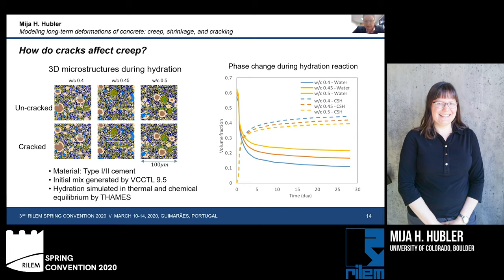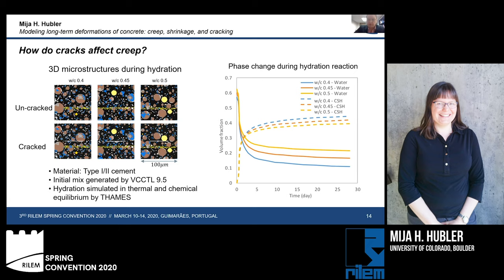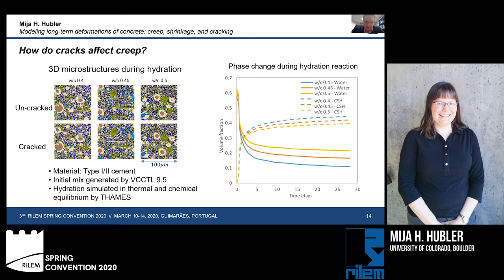On the figure on the right, you can see the volume fraction of our calcium silicate hydrate over time is increasing during the hydration process, and the water content is decreasing, which is very satisfying, telling us that this hydration process is working.